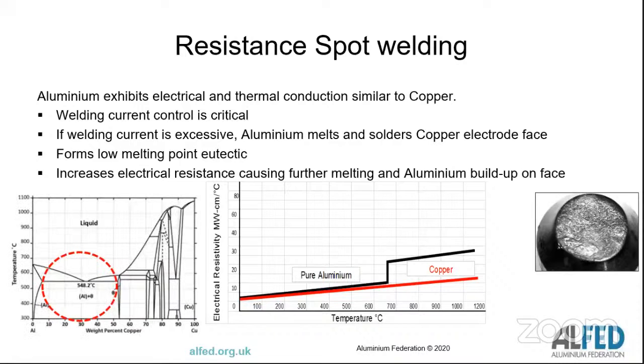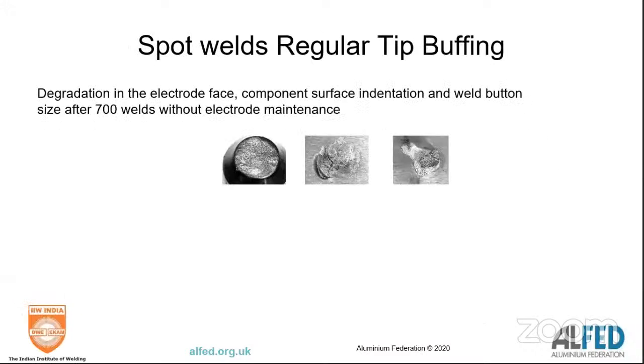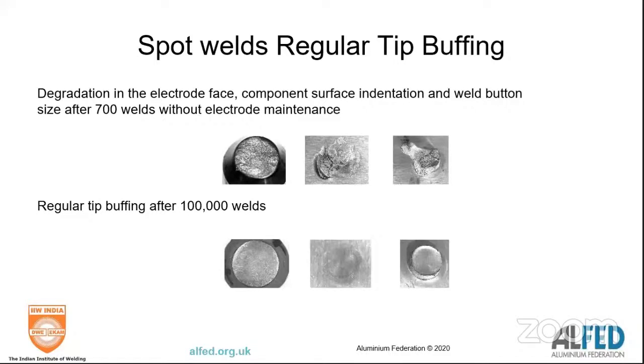That now means that you've lost your heat, the electrical resistance increases, and it'll now melt at a faster rate. So you have a problem with aluminium buildup on the face of copper electrodes. And typically, if you do nothing, you're going to get about 500 to 700 welds before you've formed an alloy and you've effectively got a splodgy electrode. So what you can do is regularly buff every 100 or so spot welds, just lightly grind the surface of the electrode.